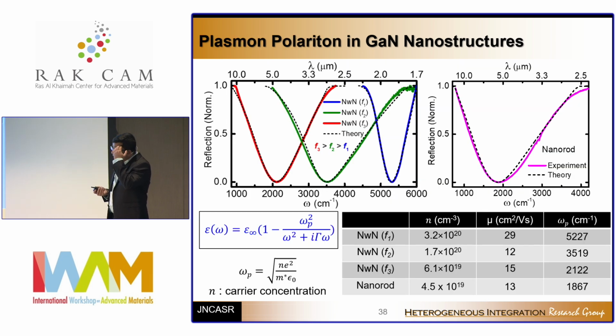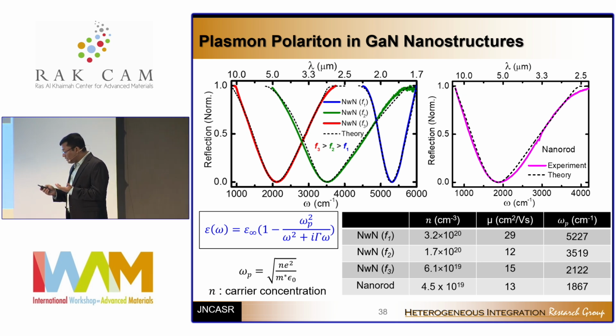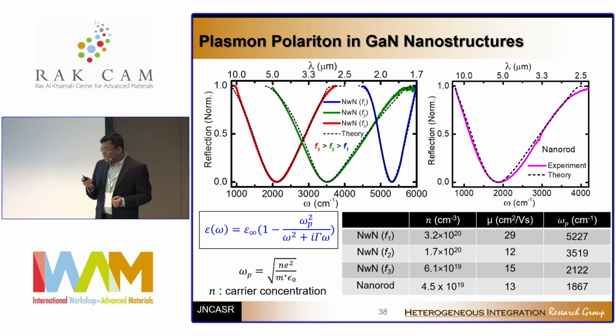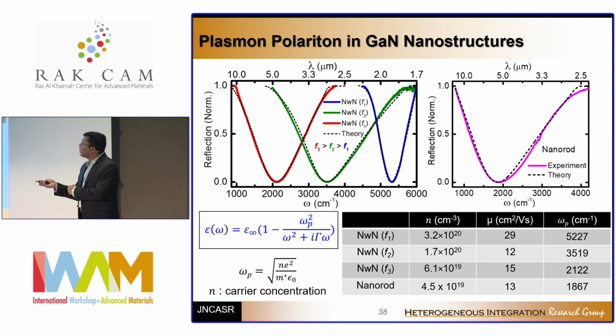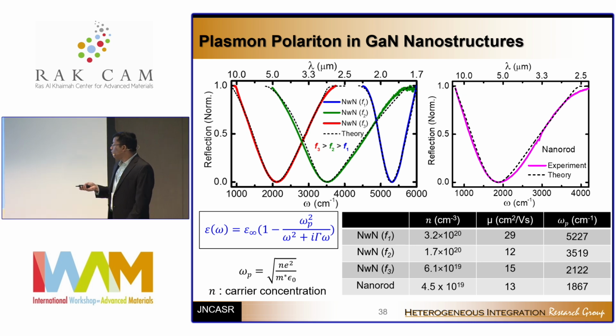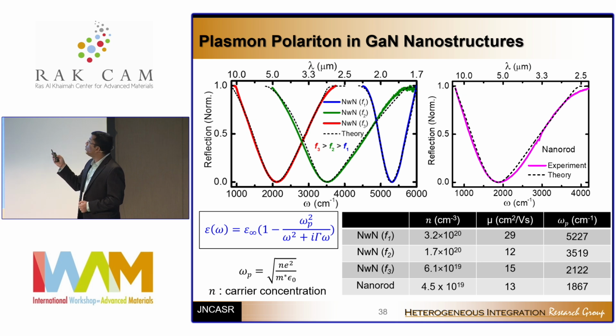Along with the phonon-polariton, we have also looked at plasmon-polaritons in gallium nitride nanostructures, because if you have a lot of surface carriers, then you have a lot of surface vacancies and surface carriers also, and that gives you a very high carrier concentration, of the order of 3.2 to 4.5 times 10 to the power 19 to 20. And if you really look at measured reflection, you can see you can excite this surface plasmon-polariton also. And their wavelength can be tuned from near IR spectral range to pretty much long wavelength IR spectral range as well, as you can see in this case.